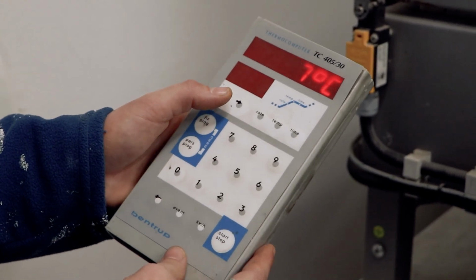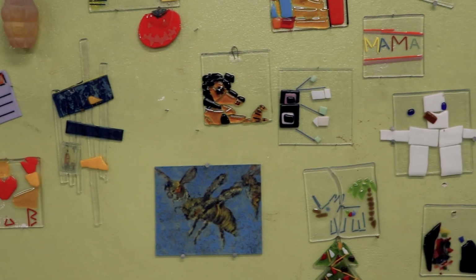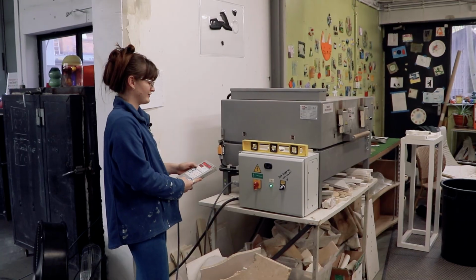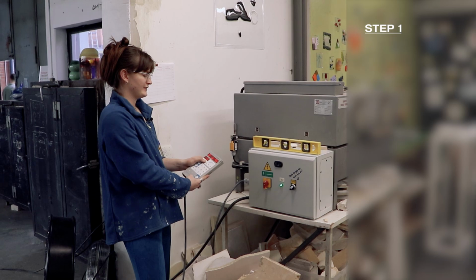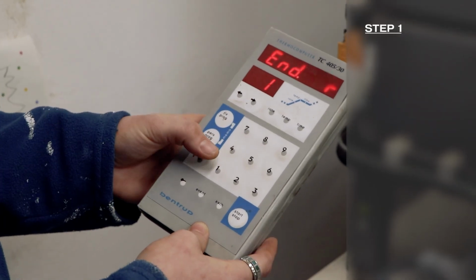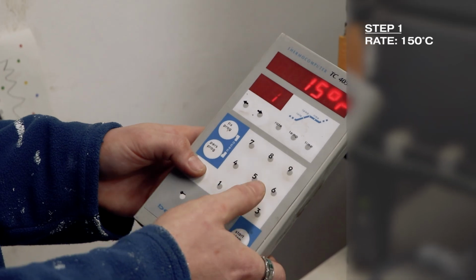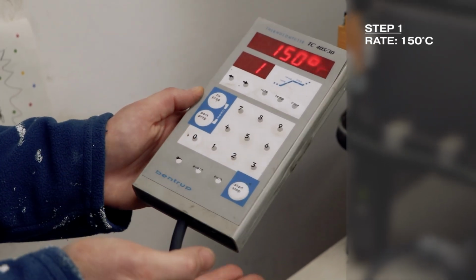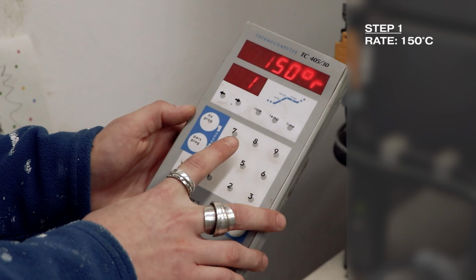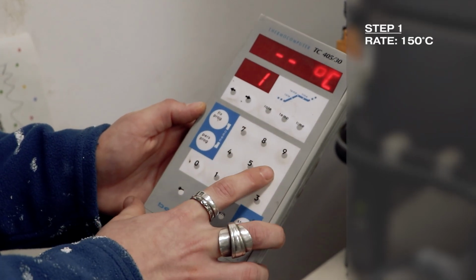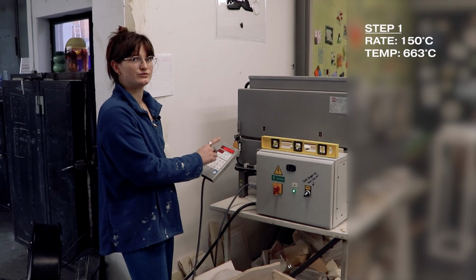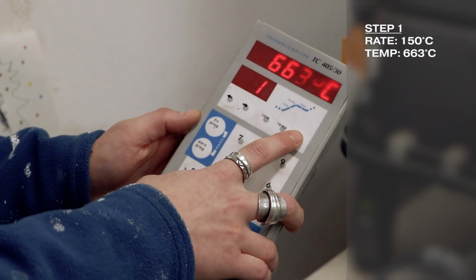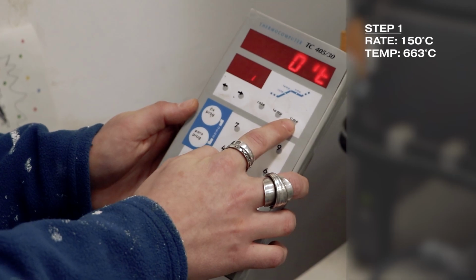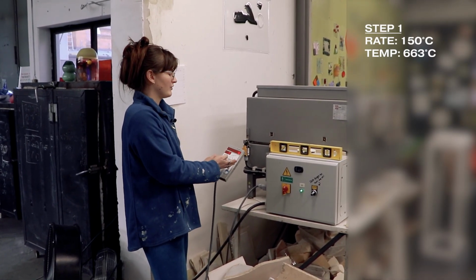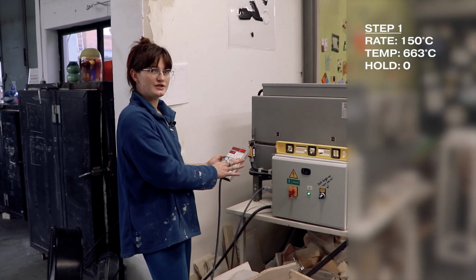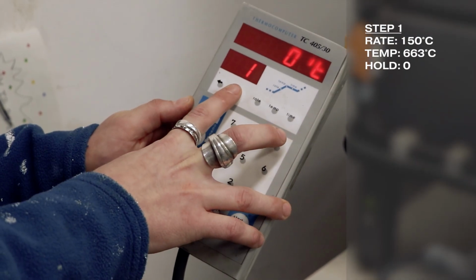Now I'm going to show you the program we use for workshop we do with kids and to fire little tiles of glass. To set your program up, you select the first step. We put rate. For this, I want 150 degrees. That means per hour, it will go up 150 degrees. So I wanted to reach a temperature of 663 degrees. So I wanted to reach that temperature in the first step. And then I want to put time, so how long it's going to stay at that temperature. For this example, we don't want it to hold any time, so we just go to the second step.